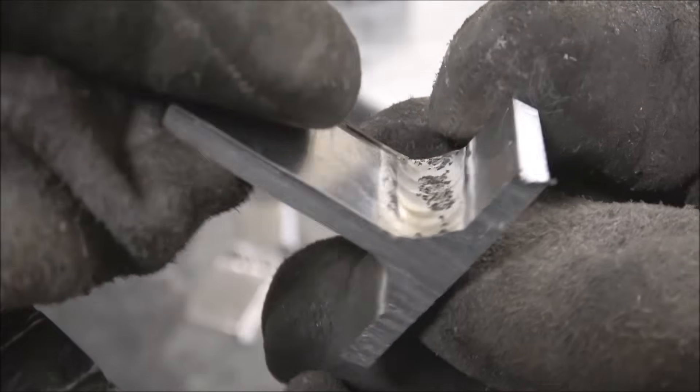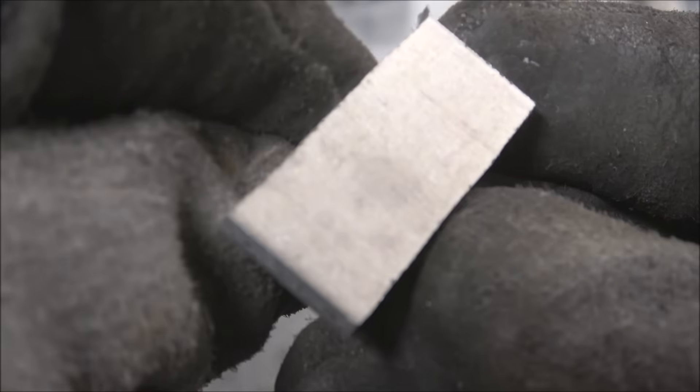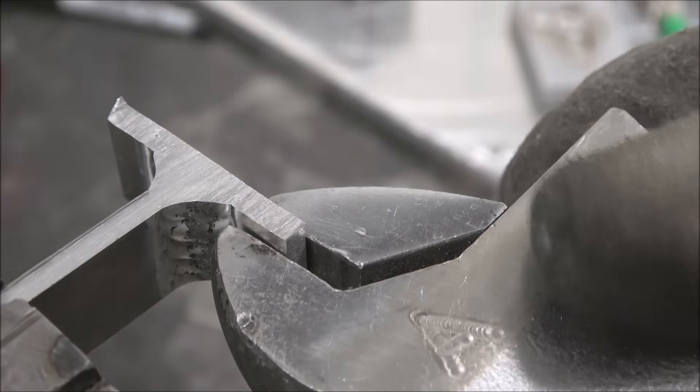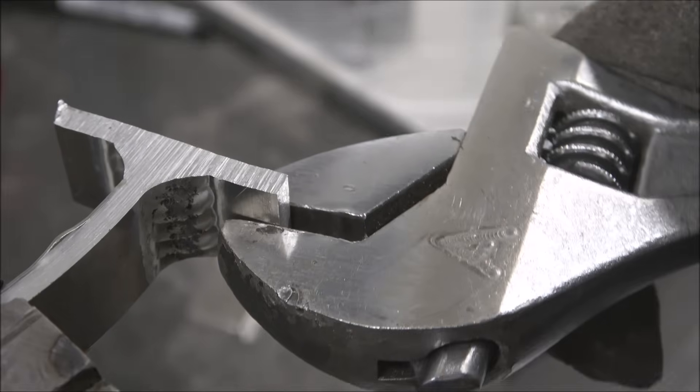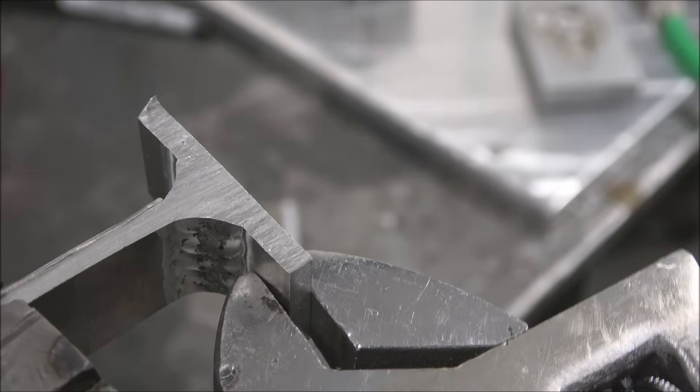This one's got a pretty decent size weld on both sides. Not quite as big and as hot as that first one. No cracks on the backside. That might have been the sweet spot on temperature and amount of filler rod. Still broke right down the edge of the weld though after several bends.